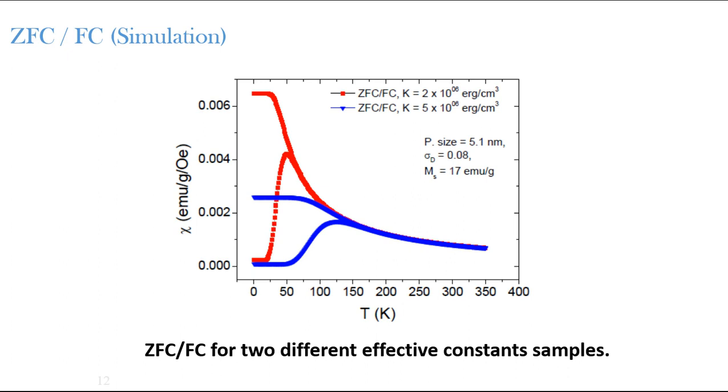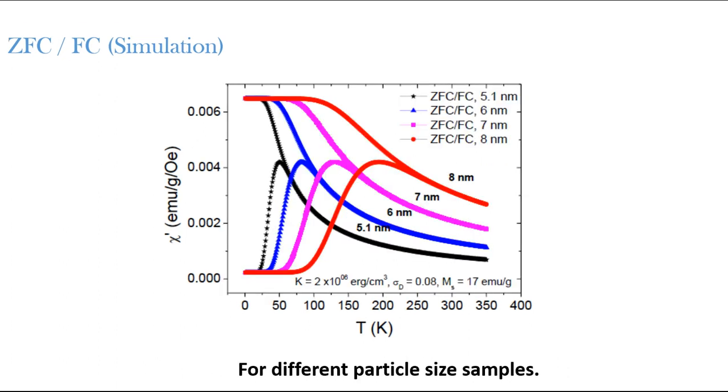Means if we need some magnetic nanoparticles to use in data storage, this TB, which for the blue curve is around 125, 130 Kelvin, should be around 300 or more than 300 Kelvin, above room temperature. So we want some nanoparticles, composite alloys, or some kind of particles which have very high anisotropy.